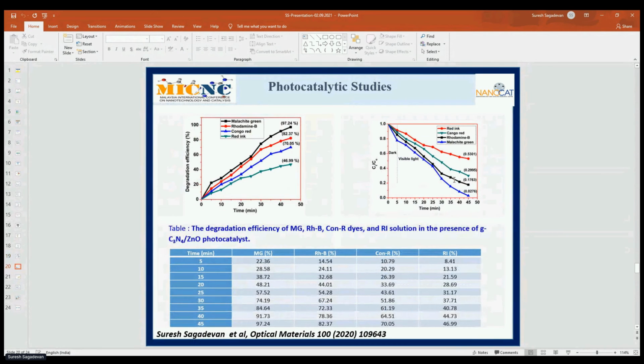Next, the photocatalytic efficiency percentage of each reaction was calculated, and the results are shown in the figure. You can see the values tabulated for the degradation efficiency of malachite green, rhodamine B, Congo red dyes, and red ink solution. From this graph, you can clearly see that the highest photocatalytic activity was observed for malachite green, about 97.24%. It is followed by rhodamine B at 82.37%, Congo red at 70.05%, and the last one, red ink, at 46.9%. From this result, the enhanced activity of the graphitic carbon nitride zinc oxide composite towards organic dye degradation is due to its interfacial structure, which helps reduce the recombination rate of photo-generated electron and hole pairs.